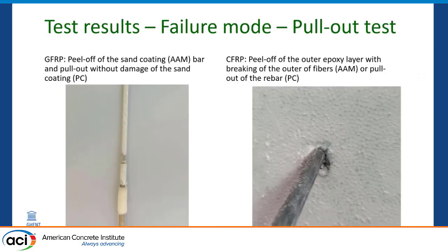So let's talk about failure mode. For the GFRP, there was abrupt failure with the peel-off of the sand coating with alkali-activated materials, and pull-out without visible damage to the bar for Portland cement. For CFRP, we similarly observed the peel-off of the outer epoxy layer with breaking of the outer fibers. That also created sort of an anchorage in the unloaded end of the rebar, or pull-out of the rebar for the Portland cement specimen.